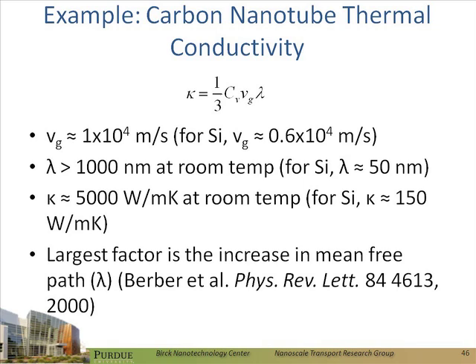But phonons still dominate. If we compare to silicon, the group velocity of phonons is 10,000 meters per second, which is respectable and higher by roughly a factor of 2 than the group velocity for phonons in silicon. This would be near the center of the Brillouin zone, the acoustic phonons. But the mean free path is the big difference. The phonon mean free path is around a micron for carbon nanotubes at room temperature, whereas for silicon, the phonon mean free path is only 50 nanometers. So that's where the carbon nanotubes have their biggest advantage: the phonons don't scatter very much.